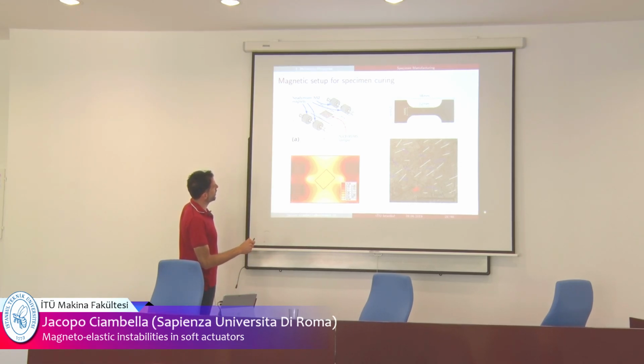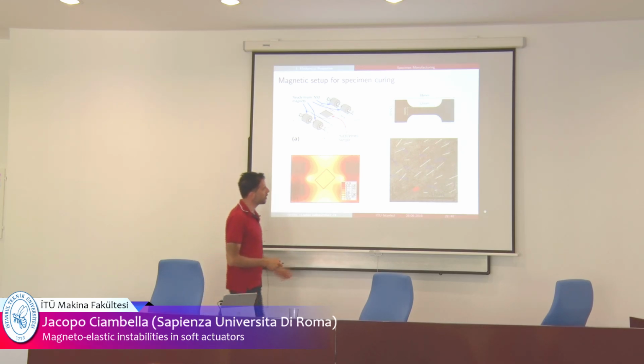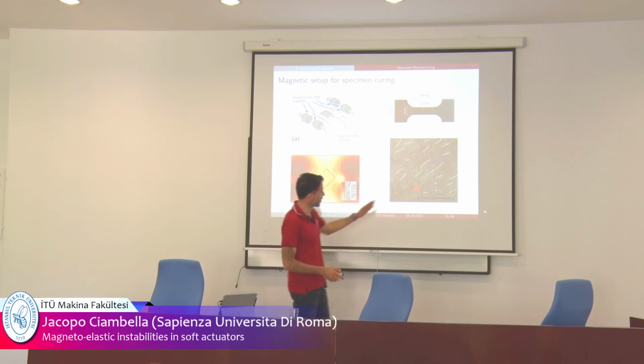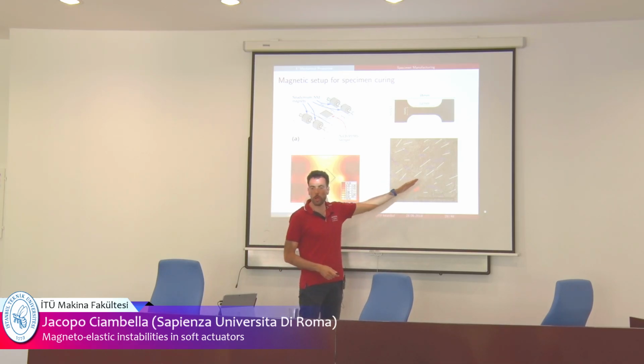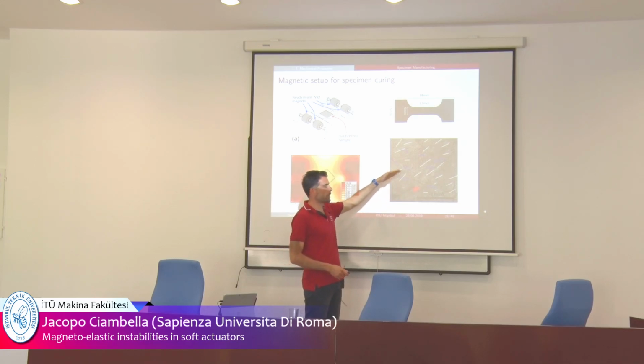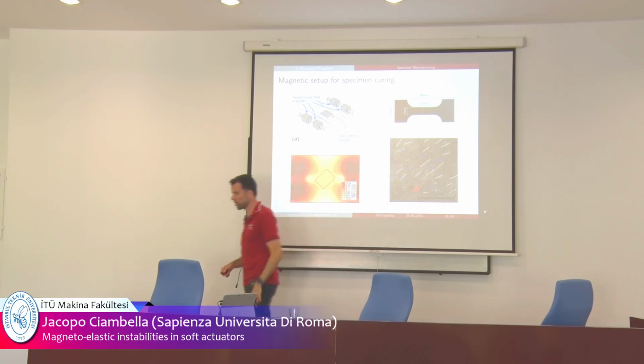So this was the Petri dish when we pour our solution, and then we cut the specimen in the standard dog bone shape, okay, with these sides. And so you can see here fiber orientation. The magnetic field was in this direction. So the white fibers are okay. The blue fibers are not oriented, probably because they lost their coating. And then you have also fiber agglomeration, which is not very good.